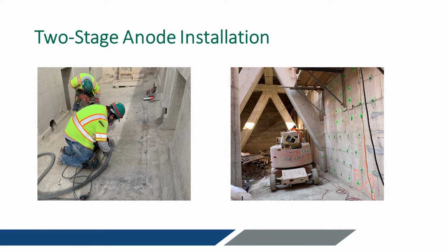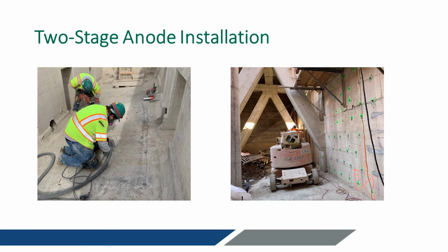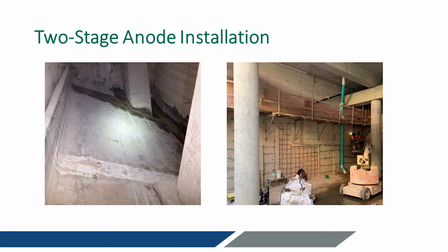And so here you can see the anodes going in on the abutment wall on the right. You can see the grid, and the abutments had a high risk for corrosion, so there's a lot of anodes over the whole surface. And then you can see on the arch floor here, there's a little targeted area that they're doing right now. So they're installing anodes and doing saw cuts to wire those anodes together, and so they'll grout those in. And then this is what the cross floor actually looks like when it's done. You can kind of see there's a line of anodes right here. They get grouted in and cleaned up, but they get embedded right into the concrete. So all those wires are embedded in, so very durable system.